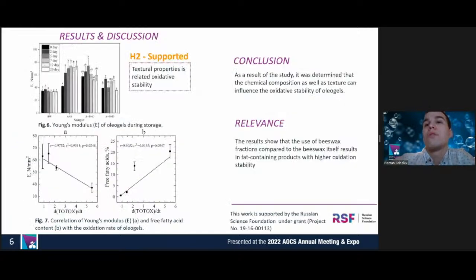Samples on a combination of fractions showed a higher Young's modulus during storage than the beeswax-based oleogel. The correlation analysis of the collected data revealed an inverse relation of Young's modulus of oleogels and a direct relation of free fatty acid concentration with the rate of oxidation product accumulation. The second hypothesis is also supported by the results.